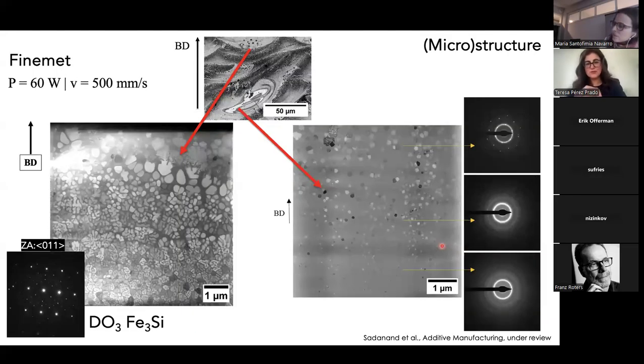Finally, if we keep zooming in, we can analyze one of these heat-affected zones by TEM. You can see here better the morphology of the crystallites. By diffraction, we can now determine that these are ordered Fe3Si structures. And if we look inside one of the melt pools, what we see is mostly an amorphous phase, as you can see in these patterns, and then some scattered nanocrystals. So this is how this composite looks.